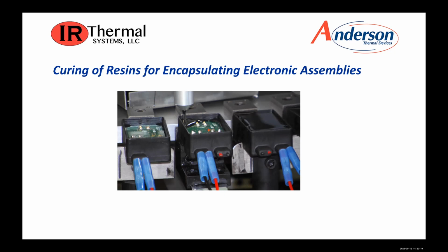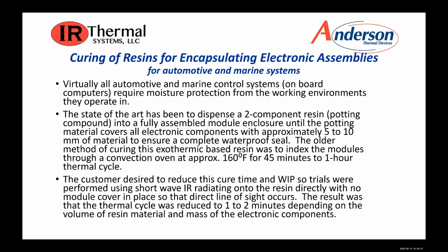Before they started to utilize the infrared, this would then go into a convection oven where it could take anywhere from 45 minutes to an hour thermal cycle, depending on the mass of the part. The convection oven had to be put at a lower temperature because the components themselves were not able to. Well, in this case, it was 160 degrees. They did not want to thermally stress the components. The answer is that because we have line of sight to the resin, we can actually see it. There's no cover on these assemblies at this point. They do cover them eventually, but they're not covered now.